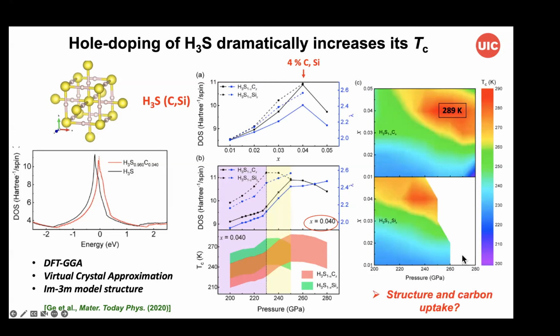And when one plots the shift in TC with impurity content and pressure, one sees a very striking increase in TC relative to H3S, from basically 200 Kelvin to something like 290 Kelvin at only 4% in the case of carbon, and something very similar happens in the case of silicon. To my knowledge, work on silicon doping has not yet been done. So this is an encouraging sign that perhaps hole doping by carbon is responsible for the TC, and this is more or less consistent with the available experimental data we have for the structure at these kinds of pressures.